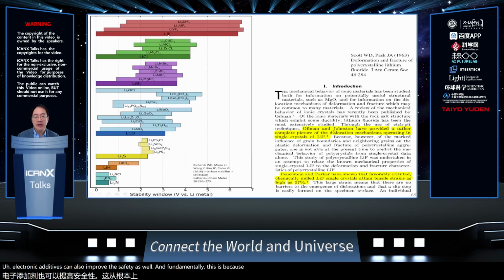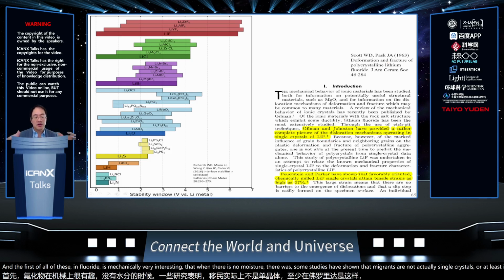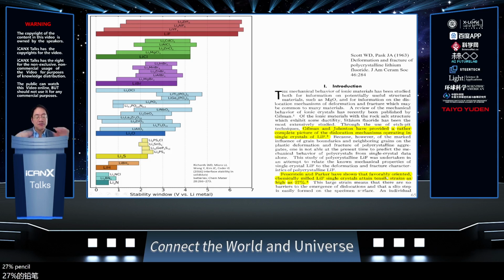And fundamentally, this is because when this fluorine-containing electrolyte decomposes, it forms lithium fluoride, which is a very wide bandgap insulator. And so you only need to decompose a very little bit of liquid to have a passivating layer on the electrode surface to stop electron tunneling. And this lithium fluoride is stable against lithium metal, but is also stable against even 5-volt cathode material. So this is useful for passivating both lithium metal anode as well as a high voltage cathode material. And furthermore, lithium fluoride is mechanically very interesting: when there is no moisture, there was some study that shows that micron-sized, not single crystals of lithium fluoride, can actually undergo 27% tensile ductility. So as a passivation layer, it can tolerate this kind of stretching inside.